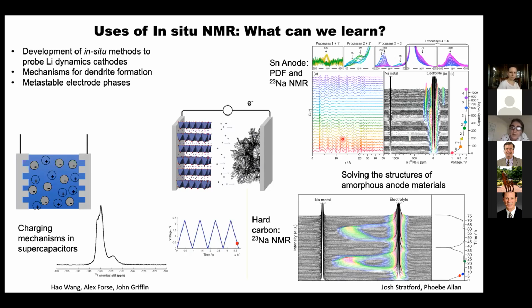And it's a very simple measure in this case to look at, for example, the crystallinity of the material. So you start with tin, and tin is crystalline. You start to then react with the sodium, and you can see by this point, you only have very short range correlations as the material becomes amorphous. And so what we do is combine the NMR information with the PDF measurements, and also we do theory at the same time to predict what phases we might see. And then we were able to solve the whole phase diagram for this chemistry.